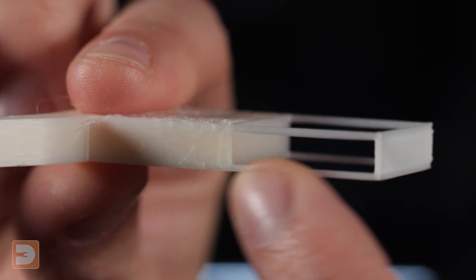That really is the main result of this test. All four filaments, whether they spent a month in a sunny window or outside braving sub-zero elements, have fared really well and they all look like they've just come straight off a print bed. They haven't gone soft, they haven't lost their detail — even that 1mm thick, 24mm extrusion bridge still looks great. You don't need to worry about a biodegradable filament giving up the ghost while you still want to use your print. It's only going to biodegrade under the right conditions for composting, so they are just as good as PLA in that respect.